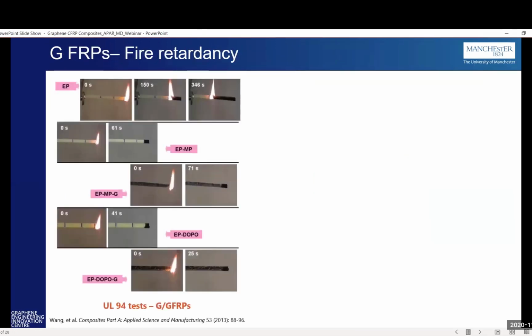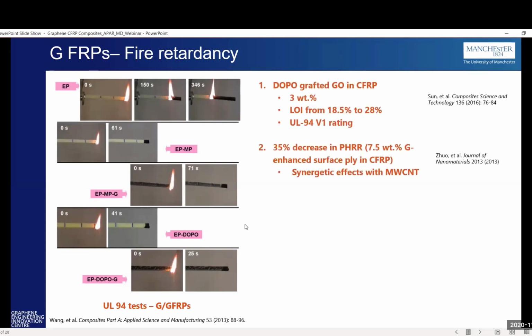So fire retardancy is another area where graphene has seen a lot of improvements. What they found is that by adding graphene along with other existing fire retardants, we've seen very good improvements in the fire retardancy. For example, DOPO is a non-halogenated fire retardant which is being used. By adding graphene to the DOPO, they were able to even improve the entire composite's UL94 properties.